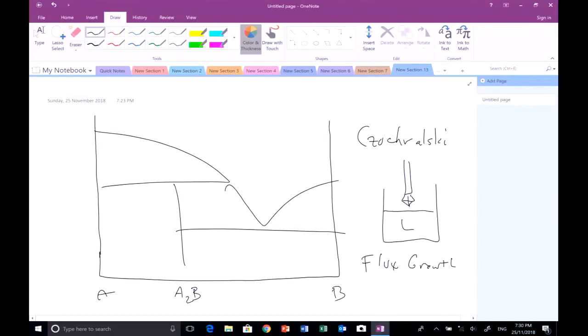And if I know phase equilibria, I'll know Czochralski is not going to work, because if I take pure A2B and I heat it up, I'm going to get A plus liquid. So my crystals are going to be wrong to begin with. So if I get a homogeneous liquid, okay, and as soon as I start to try to grow a crystal from it, all I'm going to have is the possibility of growing A. I'm going to have A2B, and it's not going to work.